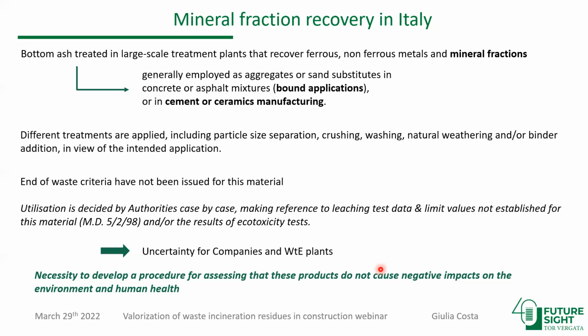Now, in Italy, the recovery of these materials, their reuse in construction, is not specifically regulated, and end of waste criteria have not been issued. Therefore, utilization is decided by local authorities on a case by case basis. Generally, they make reference to compliance leaching test data using guideline values that really have been established for other materials more than 20 years ago, such as steel slag. And in some cases, they refer to results of ecotoxicity tests.